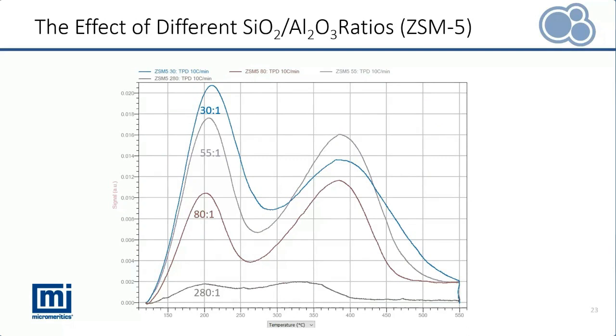Here is an overlay of the TPDs performed for each silica alumina ratio ramped at 10 degrees Celsius per minute. This trend is representative for all the ramping rates. The general trend agrees with the expected result: the sample with the lowest ratio, 30 to 1, desorbed the most ammonia, which means it displays the highest acidity. The quantity desorbed decreases in order of increasing silica alumina ratio.